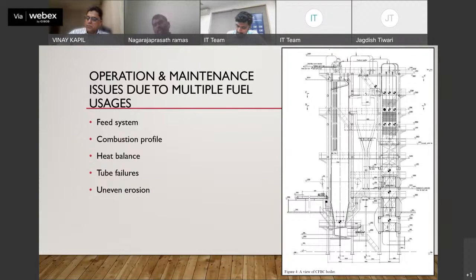But after increasing this cyclone velocity, we got a benefit in collection, but again the problem we faced is erosion in the cyclone refractories. Earlier they supplied low cement castables, but wherever we faced erosion, we completely removed this refractory and went with plastic refractory. After which the erosion came down, but still the erosion level is there even after using this plastic refractory.